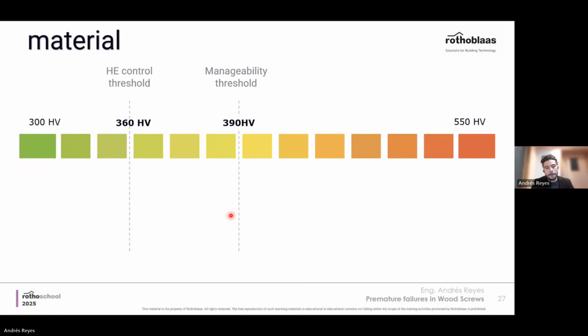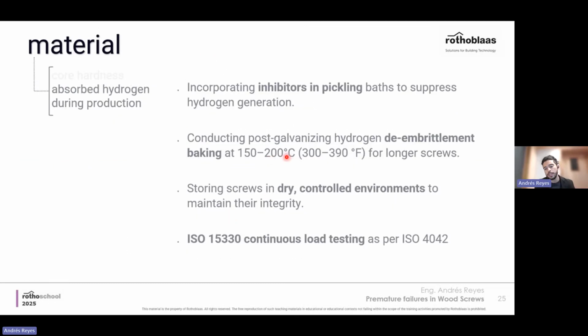And does the hardness change between before baking and after baking? Yes, and it doesn't. Hardness is affected from 200 degrees Celsius above, or 395 Fahrenheit above. So dehydrogenation baking has to be strictly below 200 degrees Celsius, so that it doesn't affect the hardness and it doesn't affect the microstructure. A baking done above 200 degrees is not a baking, it's a heat treatment process, and it would affect the final performance of the screw.